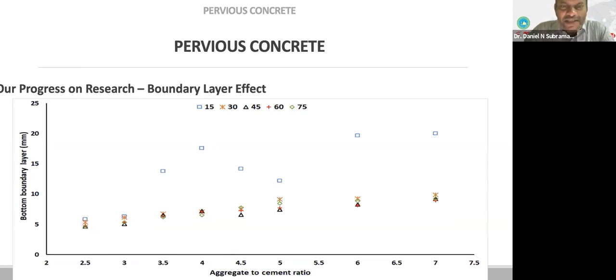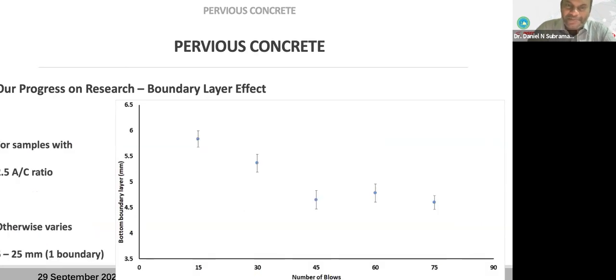So here also you can see the 15 blows has a huge variation in the boundary layer thickness with the different A/C ratios. But if you take anything other than that, 30, 45, 60, 75 blows, all give almost constant boundary layer thickness, and that is almost less than 10 millimeters for all of them. So this shows that a compaction of 30 blows is going to yield more uniform production of pervious concrete than not having any compaction.